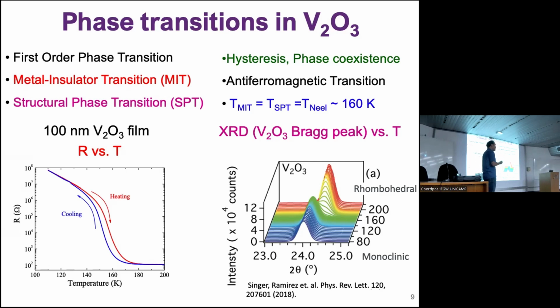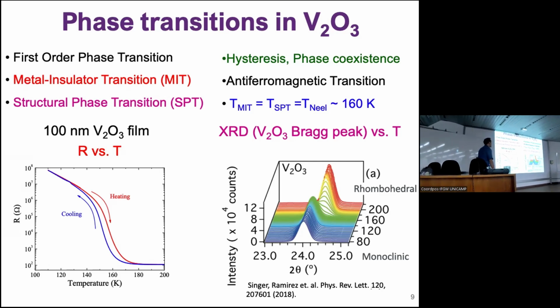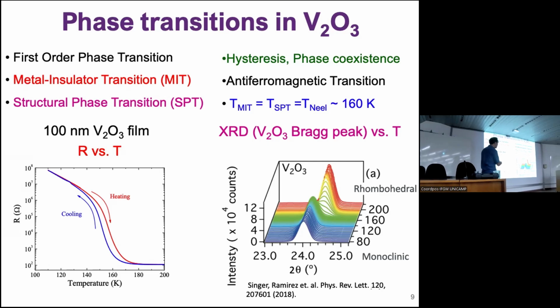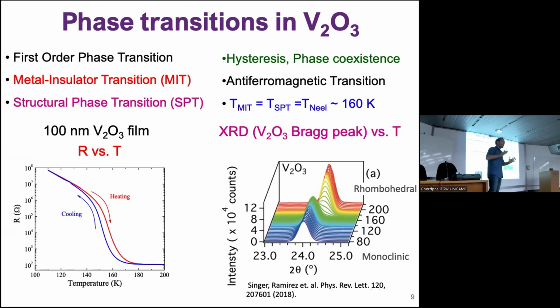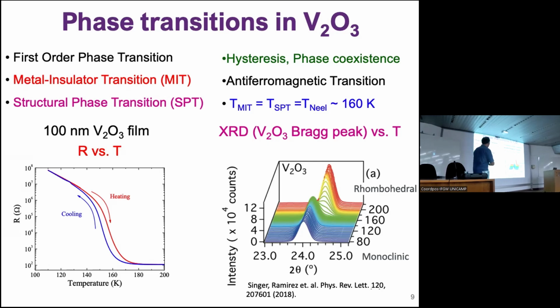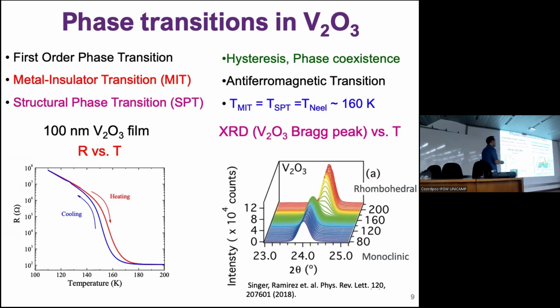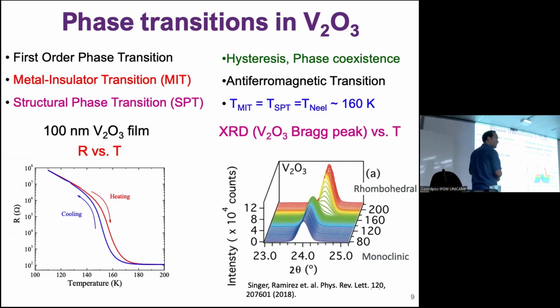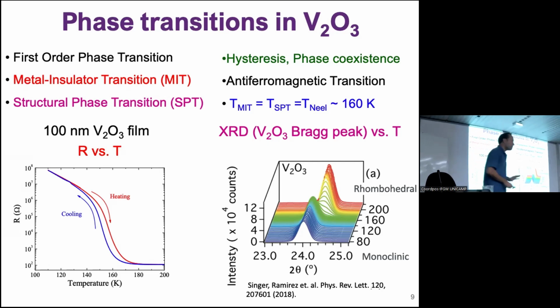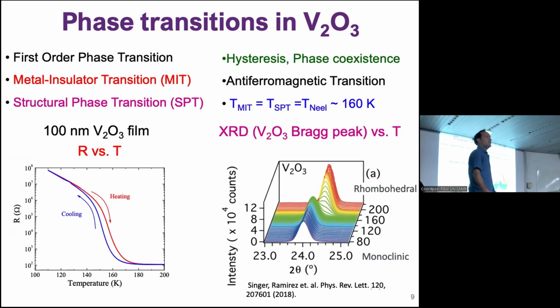And you can see here there is a huge change. This is for just one particular graphic. And this is how we used to map the structural phase transition. You see that in between, you have the two contributions of the crystallographic phases. So there is both a structural phase transition and a metal insulator transition. I spent many years trying to understand if there was a difference in temperature, trying to see if the structural phase transition was the one driving the metal insulator transition, or the other way around. So far, we conclude that these two happen at the same temperature. We don't know which one drives the other. Okay.